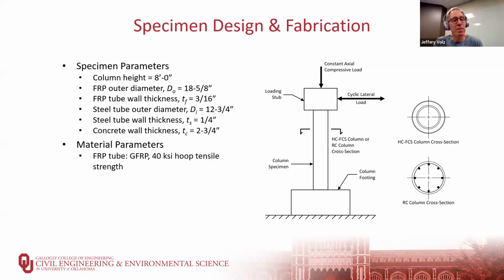In terms of material parameters, the FRP tube is glass fiber reinforced polymers, commonly referred to as fiberglass. The fibers are glass, and the polymer can be either epoxy or other types. It has a 40 KSI hoop tensile strength. That's fairly typical and is a minimum value for this application. And that's a critical design parameter because that FRP provides the confinement. That concrete wants to expand when it's under compression, and by confining it, you get a much higher apparent strength.